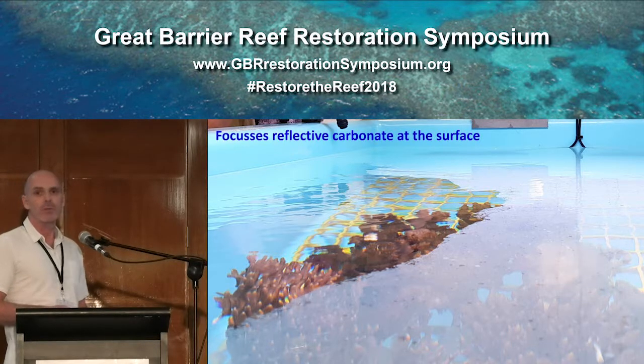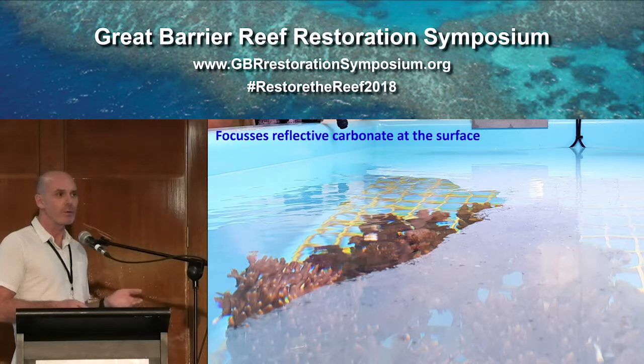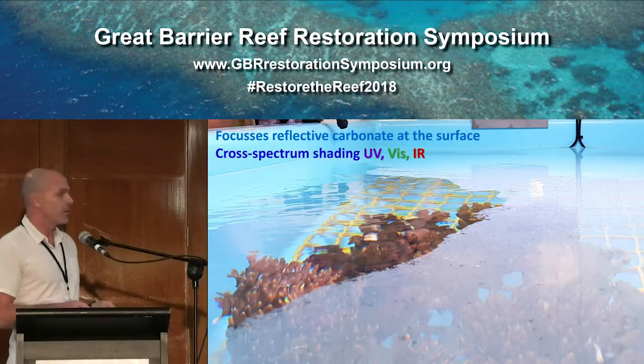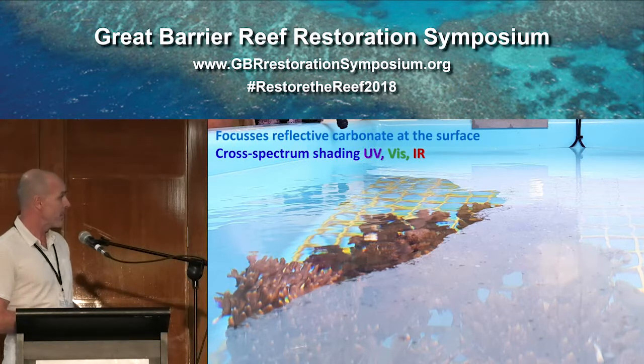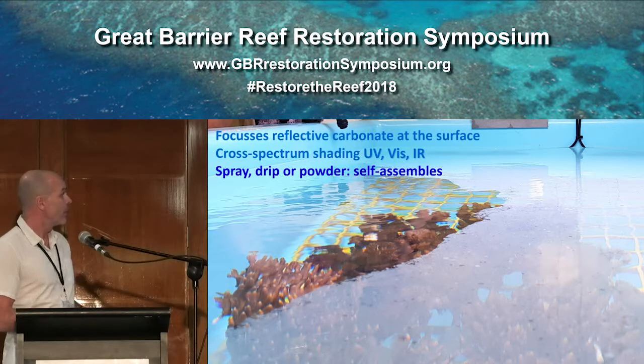We haven't done experiments on gas exchange, but there are publications which have assessed whether or not monolayers very similar to this prevent gas exchange, but don't. So that's good. There's certainly no barrier to animals. It takes no force at all to get through that film, and it simply reforms afterwards, and it's made of natural materials, and it's non-toxic.